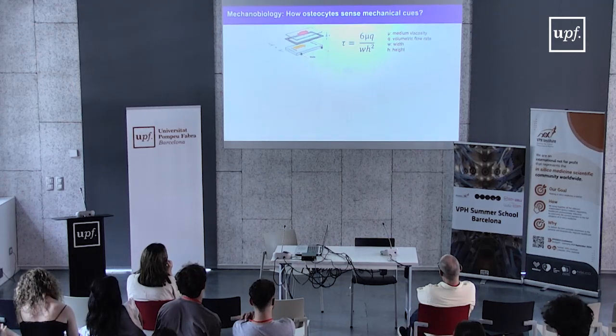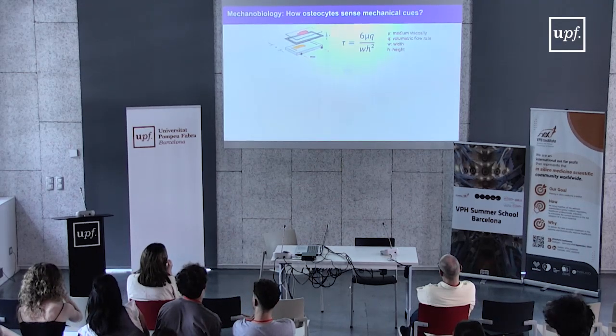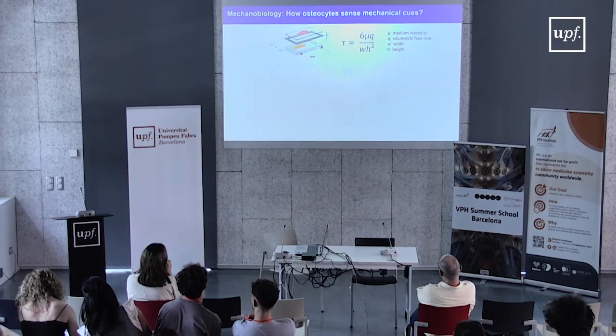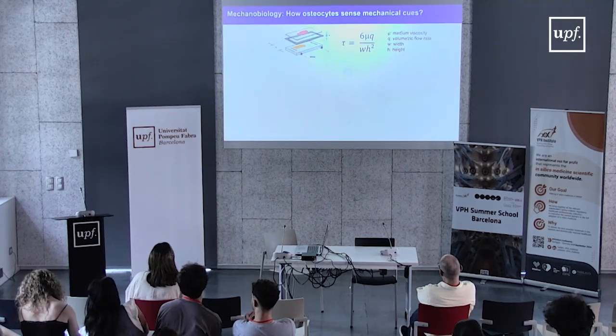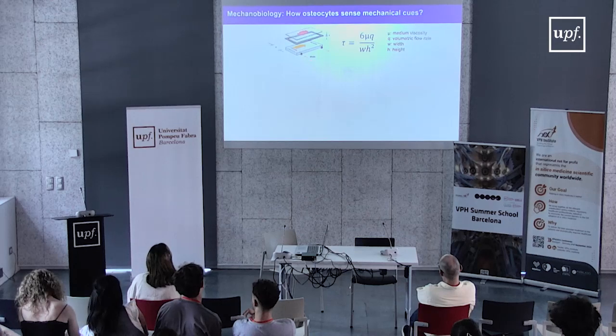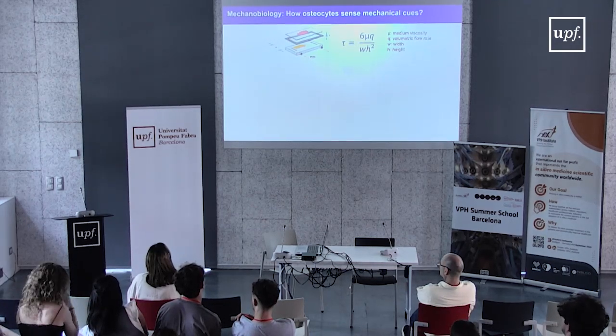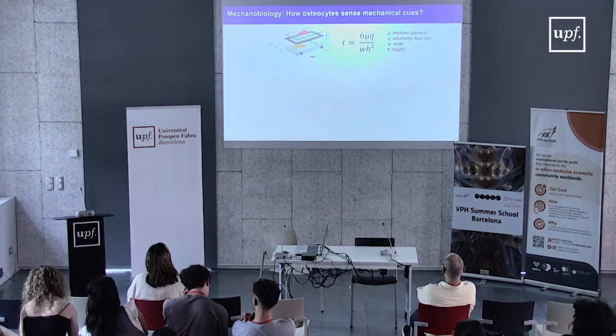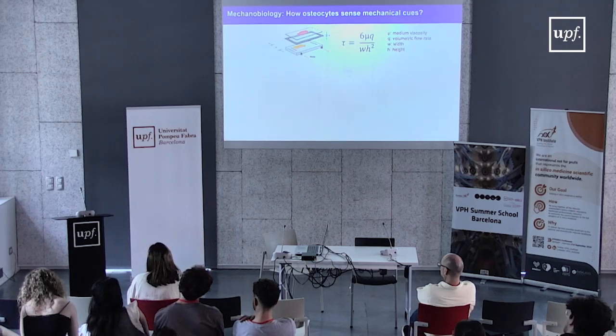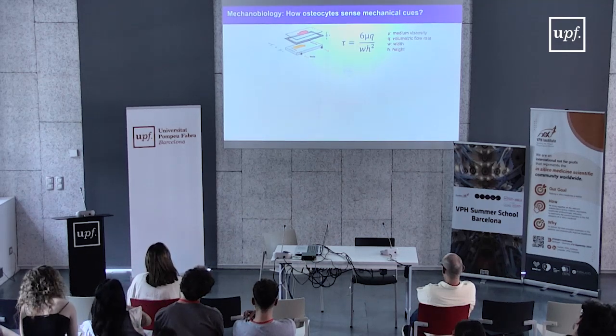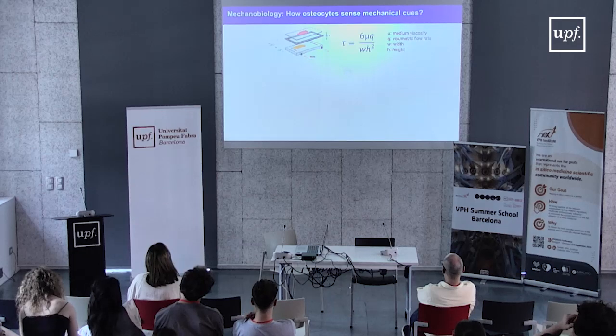How do we measure how osteocytes will respond actually to stress? It's this type of experiment that can be done in vitro with cell culture. You can just put osteocytes onto a glass plate, insert this plate into the specific device where you can induce a fluid flow inside the gasket, and you can control the stress which is applied to osteocytes through this formula, where you can adjust it with the volumetric flow rate that you will induce into the system and the width and height of the gasket.